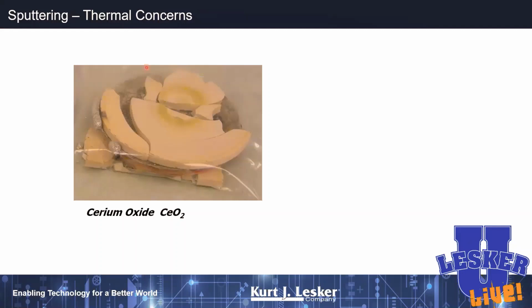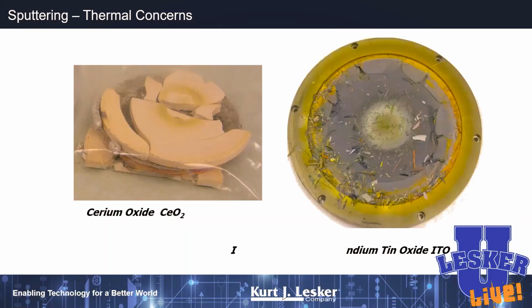If your target gets too hot, it's going to explode. If it's bonded to a copper backing plate, you're going to melt it off the backing plate. You might even disassociate the material. This is indium tin oxide, and you can see this got so hot that we actually disassociated the indium tin oxide. We've got indium oxide out here, and then lots of cracking.